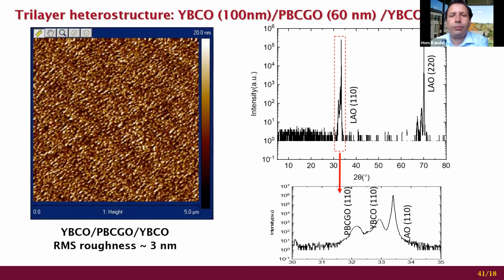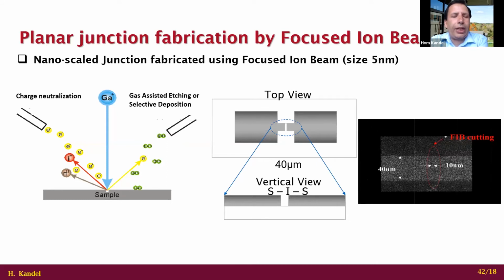So next slide, please. We have also fabricated a planar type of junction, YBCO planar junction, and we have filled it with silicon dioxide just to optimize our growth process for SIS tunneling Josephson junction device. On the right-hand side, this is the picture of this FIB cut of the tri-layer structure with silicon dioxide as an insulator. We have performed some IV characteristic studies, and we have also measured the J sub C value, but for the time limitation of 8 minutes, I didn't like to include that one.